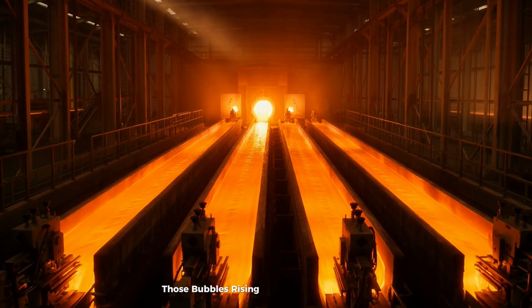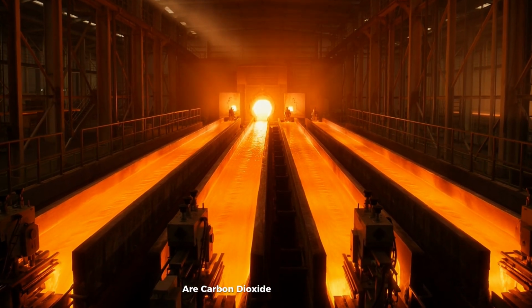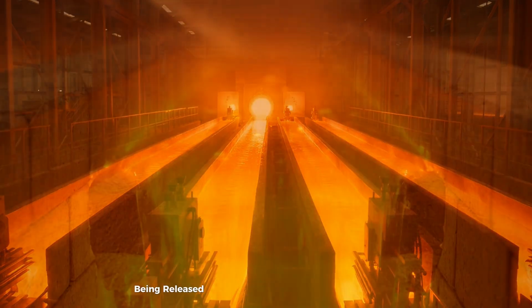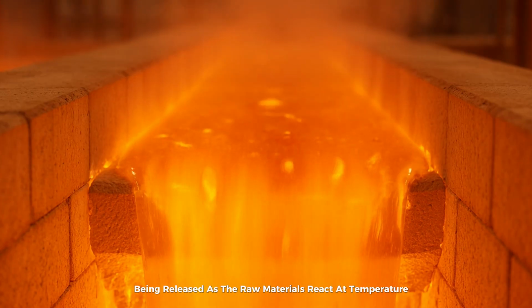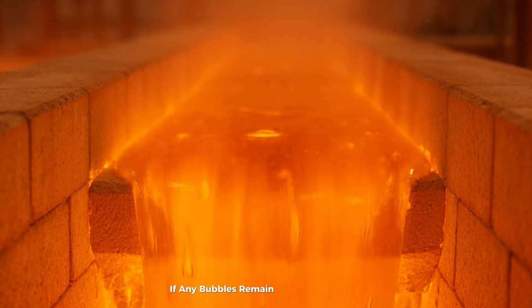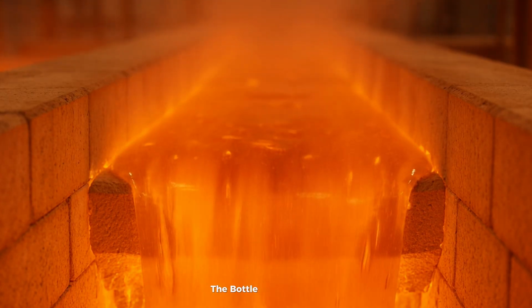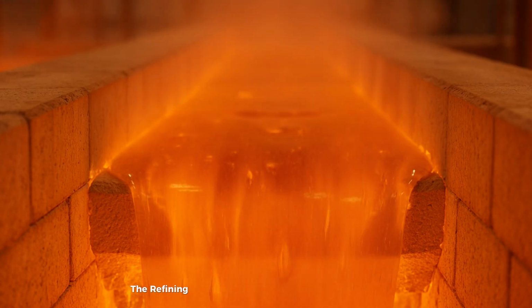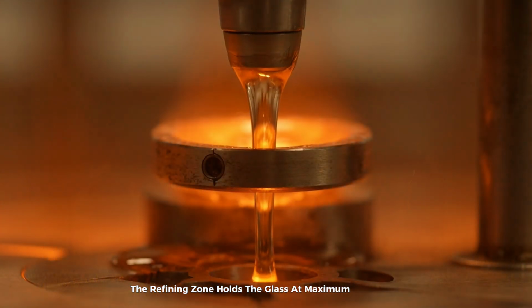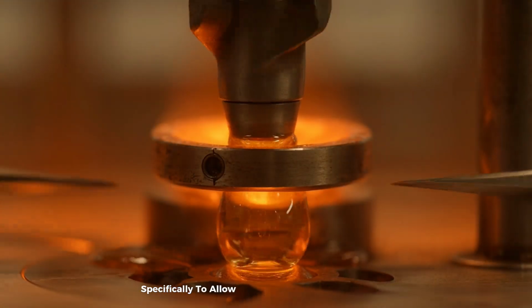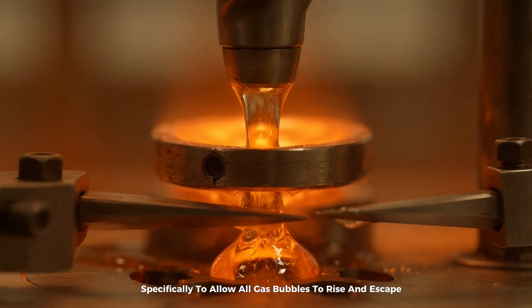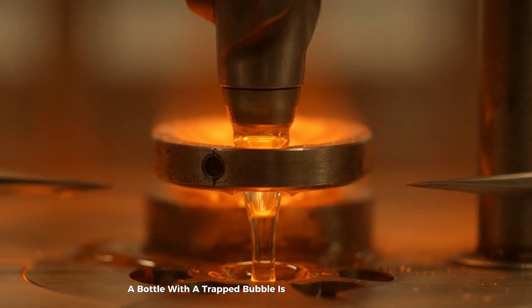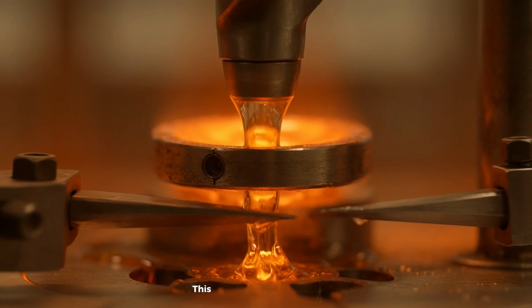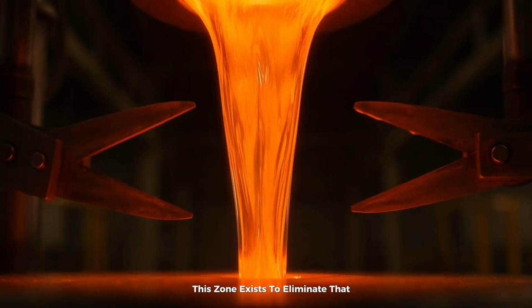Those bubbles rising through the molten glass are carbon dioxide and sulfur dioxide being released as the raw materials react at temperature. If any bubbles remain in the finished glass, the bottle fails inspection. The refining zone holds the glass at maximum temperatures specifically to allow all gas bubbles to rise and escape. A bottle with a trapped bubble is a bottle with a weak point. This zone exists to eliminate that.